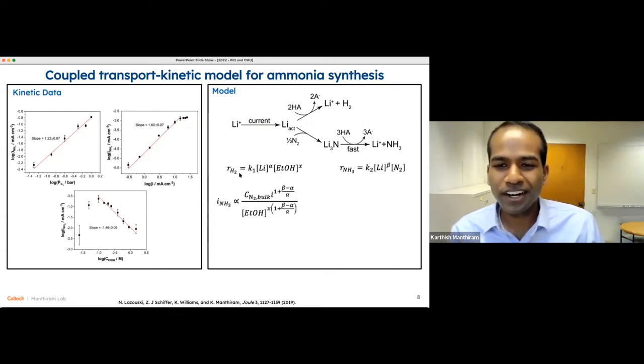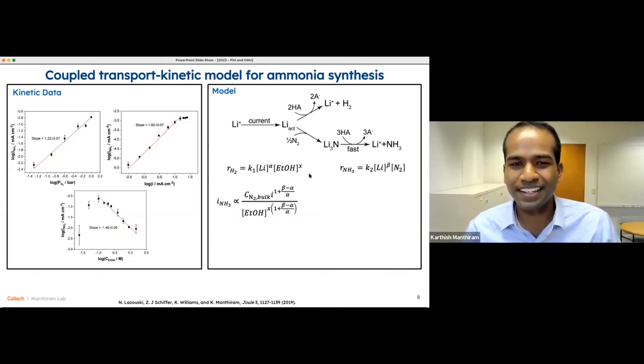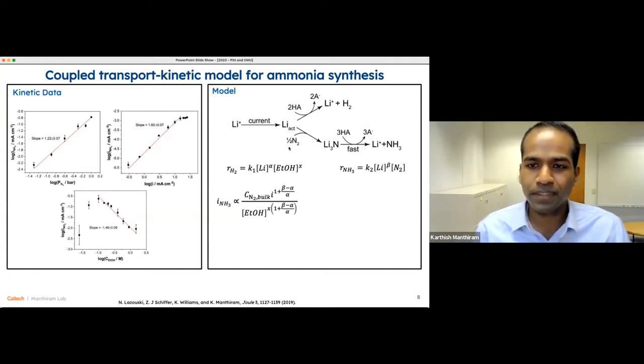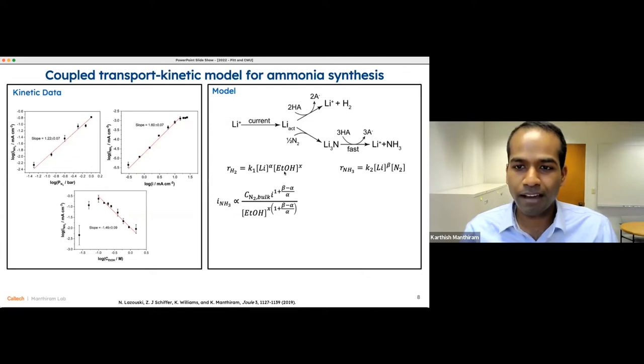We can write out really simple rate laws for these reactions. And this really, for me, connects back to things that we learn even in undergraduate kinetics. So you'll see this model is actually pretty simple. The rate of hydrogen evolution, which is this branch up here, is some rate constant K1 times lithium right here raised to some power alpha, which we keep arbitrary for the time being. And that lithium is reacting with ethanol, so we have that raised to some arbitrary power X. The rate of ammonia synthesis, so the product here, is some rate constant K2 times lithium raised to some power beta times nitrogen. And we already know that its order dependence is 1 from here, so we've gone ahead and enforced that.